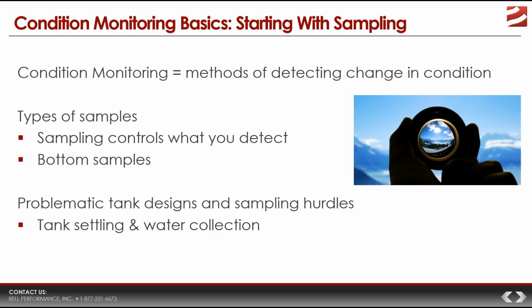Now, reconcile this practical fact with the fact that for underground storage tanks, you have certain regulations that mandate that the tank is supposed to be trimmed by the fill end, is what they say. What that means is it's supposed to be either level or slightly lower at the fill end, because, of course, the fill end is the place that's easiest to get water out of. So they want the water to roll down to that end. Yet, because of the weight of tanks, once they're put into the ground, they almost always settle into their backfill. And they settle in certain ways. Most commonly, they'll settle at the turbine end, which gives us that problem we just talked about. Tanks do not settle evenly. They settle unevenly, and how they settle affects where the water accumulates in the tank.